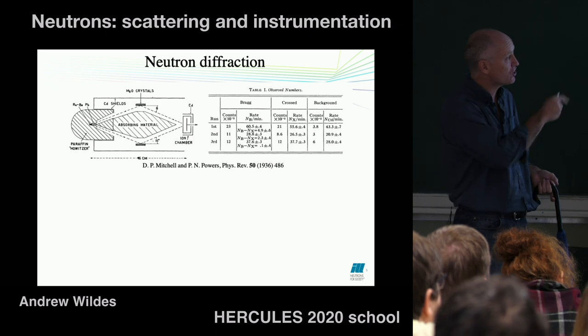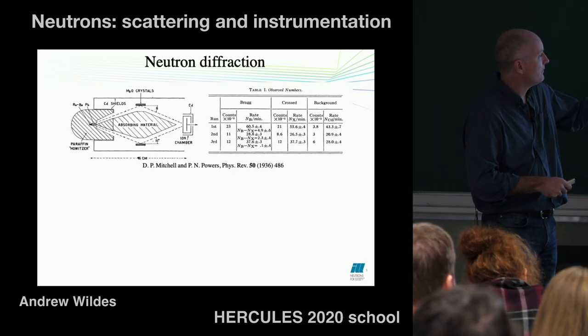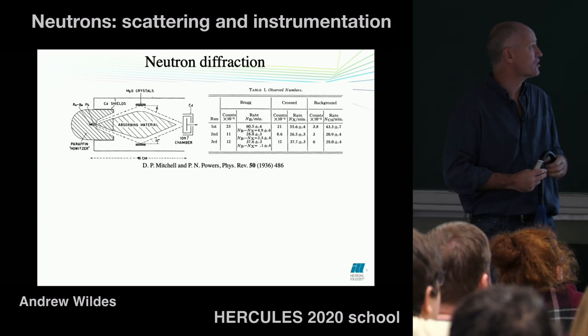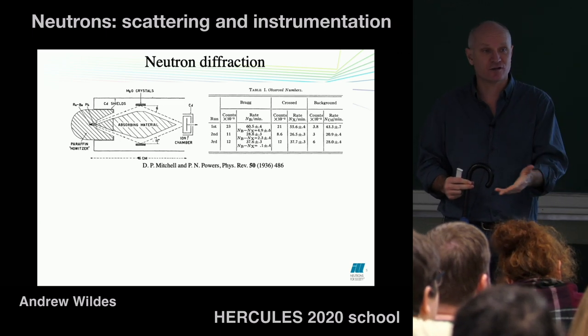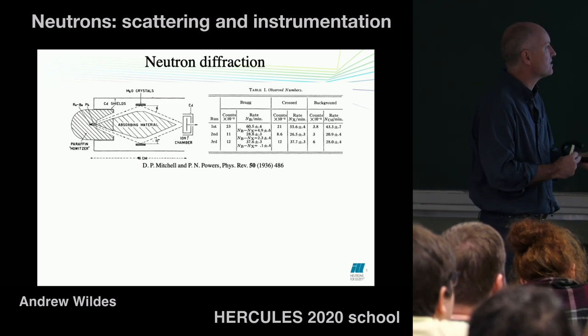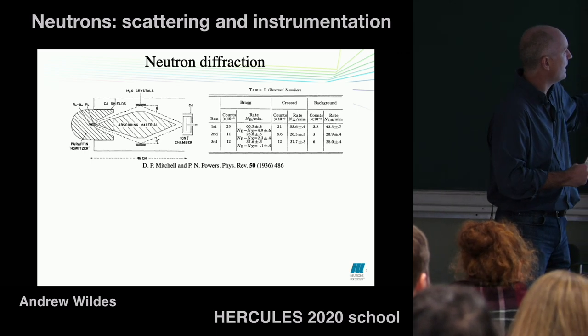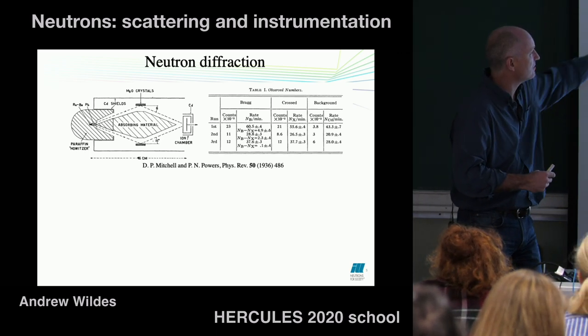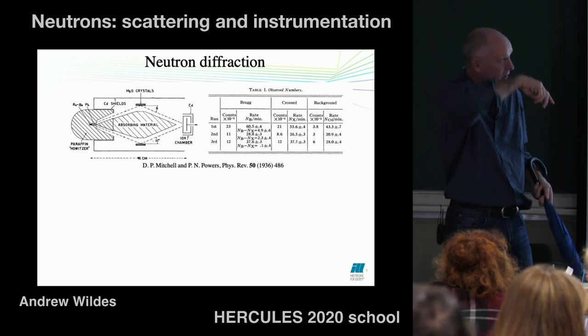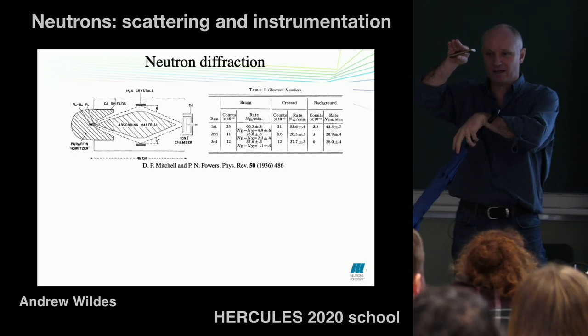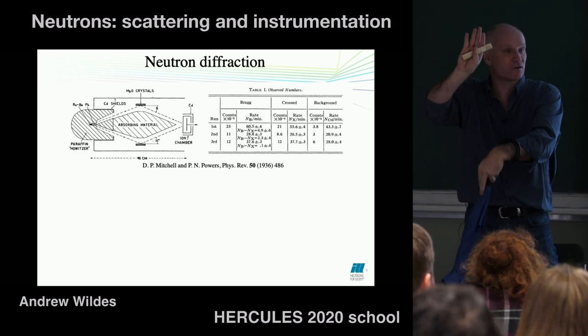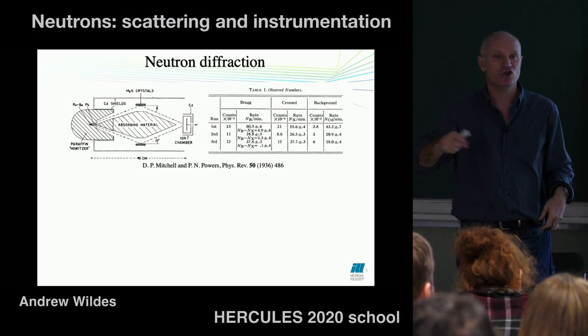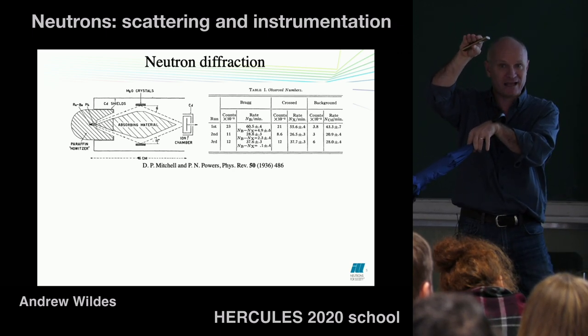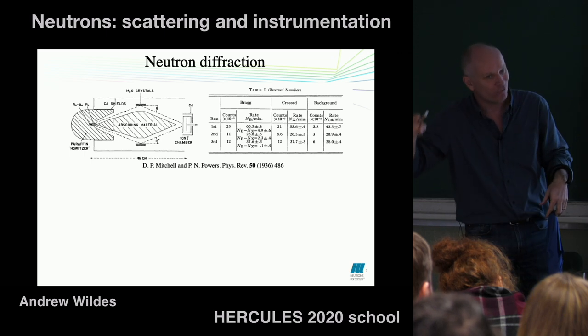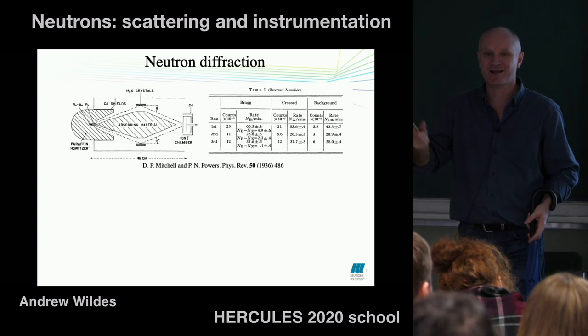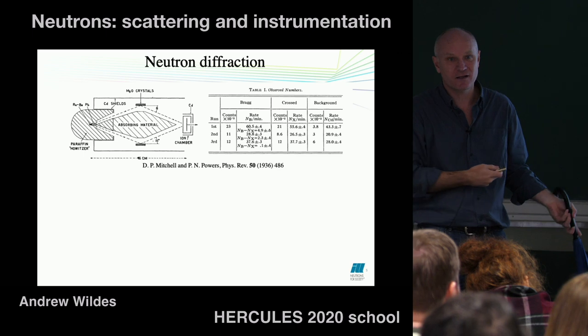Right, so this first measurement that I showed you yesterday as well, this is one of the first measurements of neutron diffraction. And the way they set this up is they've got a source in here, they've got two crystals, and they set them up at exactly the Bragg angles. They do a measurement with them exactly at the Bragg angles, and then they rotate the crystals a bit so they're no longer at the Bragg angles. You measure the number of neutrons at the Bragg angles, you measure the number of neutrons not at the Bragg angles, you look at the difference, and you see if there's an increase. That's the way they did the experiment.